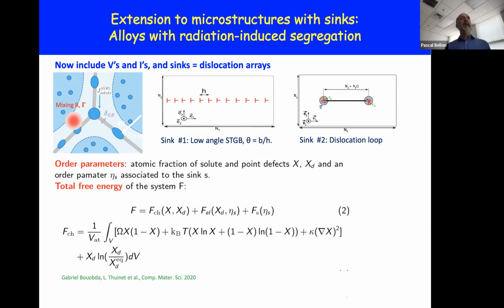We know that in some cases point defects start forming clusters like di-vacancies, tri-vacancies, and potentially we would want to include those defect clusters, but it becomes complicated because, as you realize quickly, if you describe those objects or defects by fields and they form clusters, this is not a good problem for phase field modeling. Right? Yeah, correct. I agree.